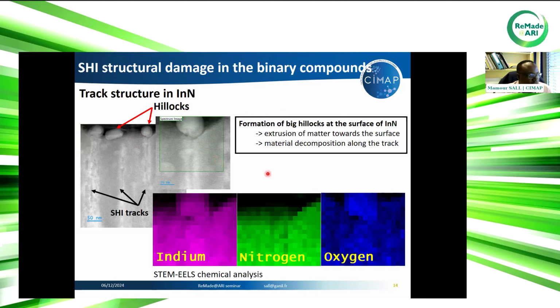Another thing we can see here is that the hillocks show dissociation of indium nitride. We have performed here STEM-EELS chemical analysis of this part of the sample. So we have a hillock here and the track below. What we can see here is that the hillock is only made of indium. There is no nitrogen. So this means that indium nitride dissociates along the ion track. And of course, we have oxidation of the indium when the sample was put in air after irradiation.